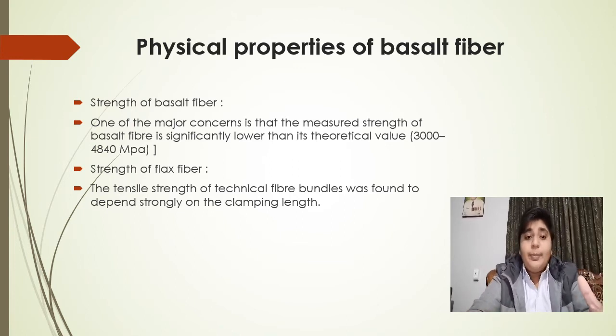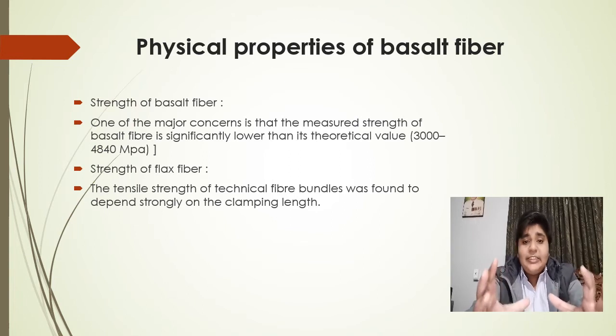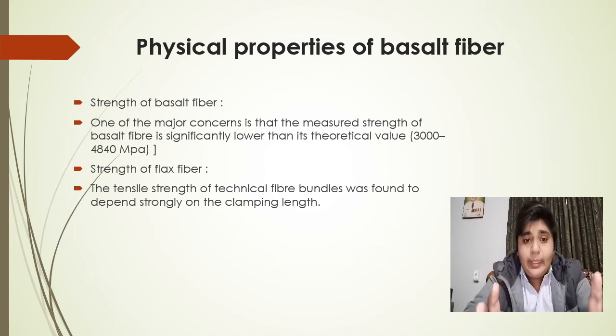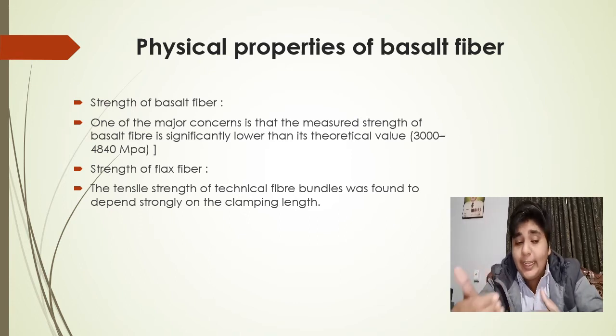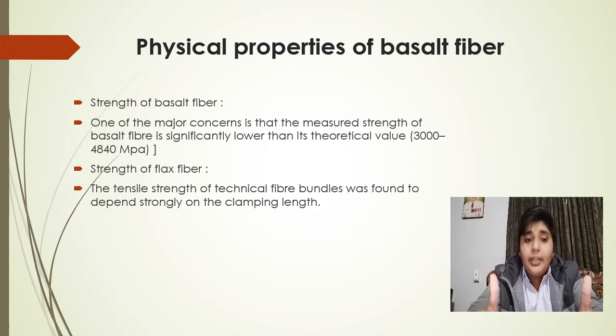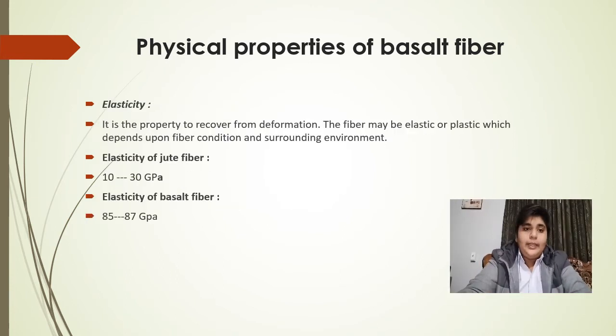And the next one is the strength of basalt fiber. One of the major concerns is that the measured strength of basalt fiber is significantly lower than its theoretical value of 3000 to 4840 MPa. This is due to the existence of defects in the form of scratches. Strength of flax fiber. The tensile strength of technical fiber bundle was found to depend strongly on the clamping length. The tensile strength of elementary flax fiber was found to range between 1500 MPa and 1800 MPa depending on the isolation procedure.